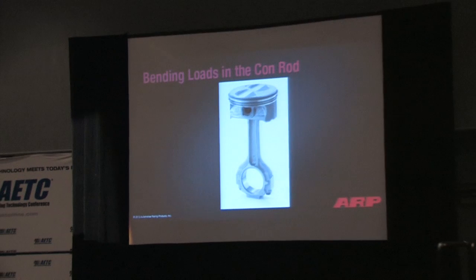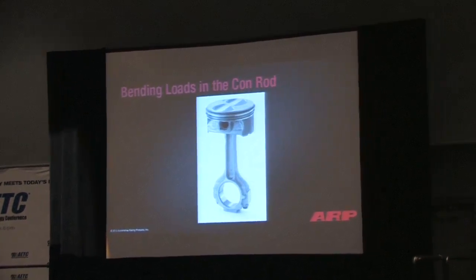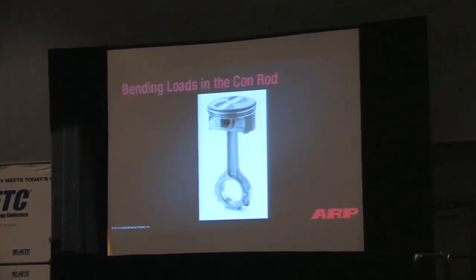Now, I threw this slide up here to be politically correct. This is actually a GM LS7 titanium connecting rod. The reason for putting it up is to point out that when the thing's running at RPM, there's actually a bending load that goes on in the big end of the rod here. So at top dead center, you've got a load that's being exerted by the piston and the rod trying to throw itself off the crank. What that does effectively is put a bending load at the parting line.